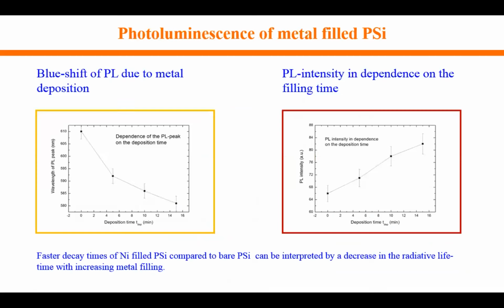Photoluminescence investigations show a blue shift of the photoluminescence peak with increasing deposition time. And in the right diagram, you see an increase of the photoluminescence with increasing metal deposition. So we also looked at the decay times of the samples, and faster decay times can be interpreted by a decrease in the radiative lifetime with increasing metal filling.